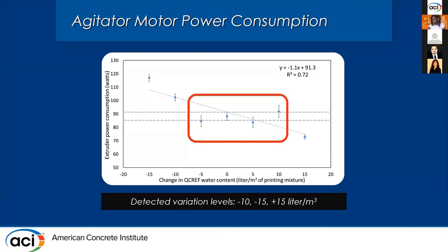And also another observation that I had was that in the lower level of water content, like -10 and -15, we had a bigger change in the power consumption. So basically there was more response in the power consumption when we had more viscous printing material compared to +10 and +15 liter per cubic meter. So the system was more responsive when we have a lower amount of water and more viscous mixtures in the hopper agitator system. And based on that, the variation levels that basically were detected by this technique were -10, -15, and +15 liter per cubic meter.